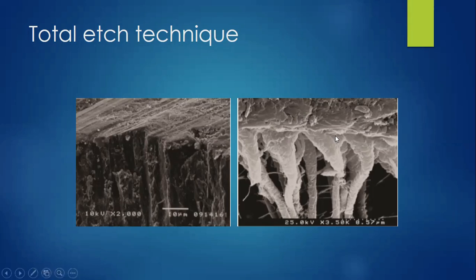They will lead to degradation of this layer. So various studies have been done on how we can prevent this degradation. It has been said that using chlorhexidine 2% for 60 seconds on phosphoric acid etched dentin before using etch and rinse systems can to some extent reduce this degradation by MMPs.